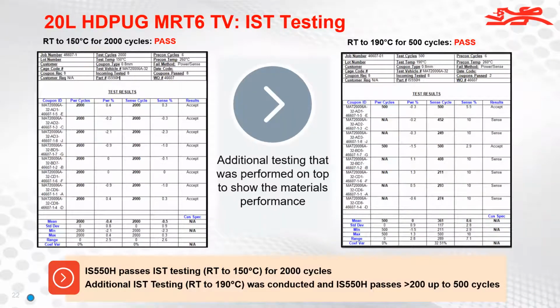This is some of the IST testing. And so thermal cycling, this is one of the areas that people are most concerned about. And so this type of testing is critical to understand with regard to how this material performs. And so this test here is just a room temperature to 150 degrees C cycle testing. And so it simulates some real world type of environments. But what's really interesting about this particular material, we ran it at 150 degrees C, and then we thought, well, let's crank it up a bit.